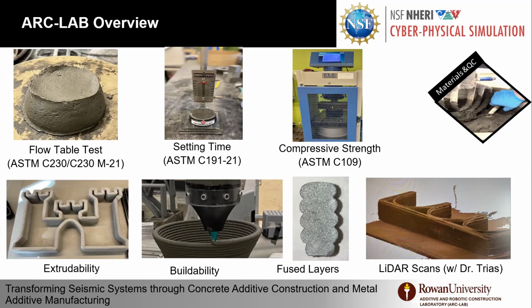And as you can see here, how it looks as a material is a fused layer from a cross section that we cut through the material. You can see the layers from the outside, but it's really fused with the technique that we use. And we are very happy with the product. We also collaborate with Dr. Trias from Rowan University on using LiDAR to capture geometry and identify cracks as we print.